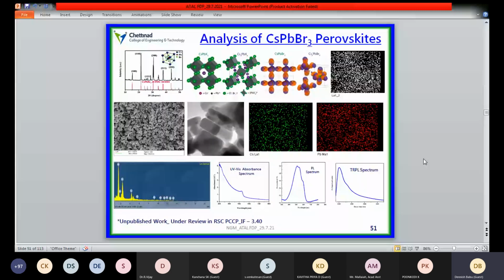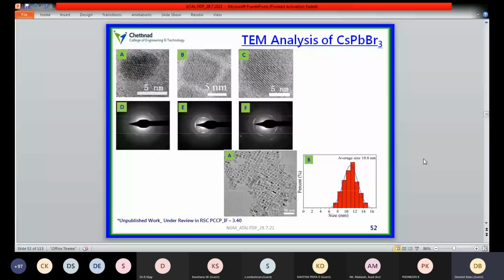and they come as a kind of nano brick structures. Some kind of structure has been identified from the cesium lead bromide system. Also we have played with cesium lead bromide with different structures, like ABX3 to A4B6, a new kind of cesium lead halide perovskite system. That also we have prepared with the help of hot injection based synthesis. So this is the TEM analysis of the cesium lead bromide system. Very fine single nanocrystals are easily identified with the help of TEM analysis, and the average size of the prepared materials lies in the range of 10.8 nanometer only. Very fine tuned, controlled nano.